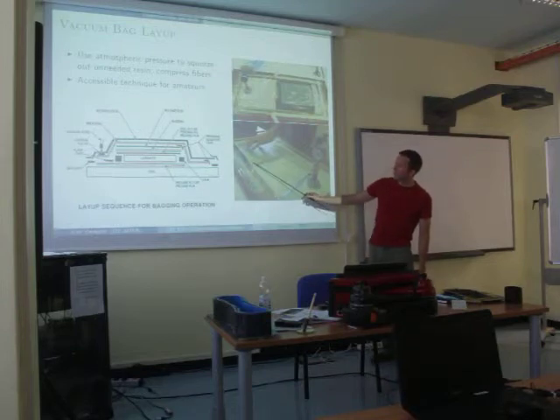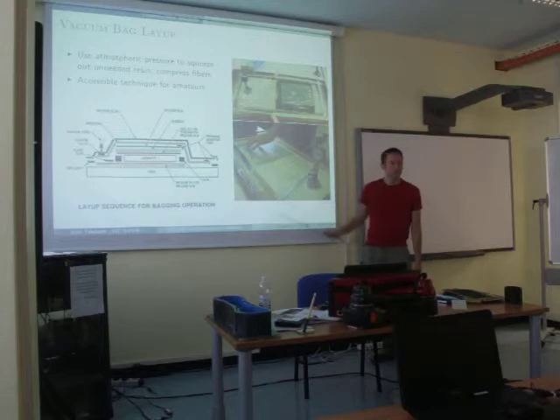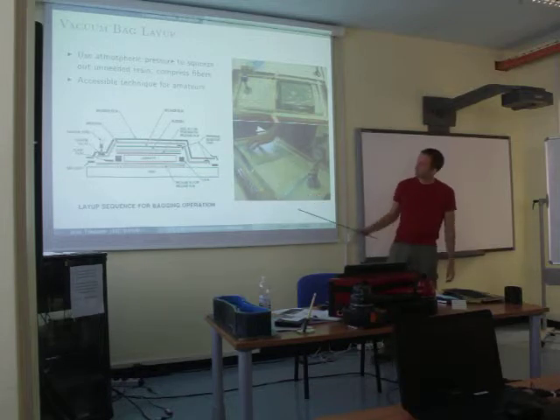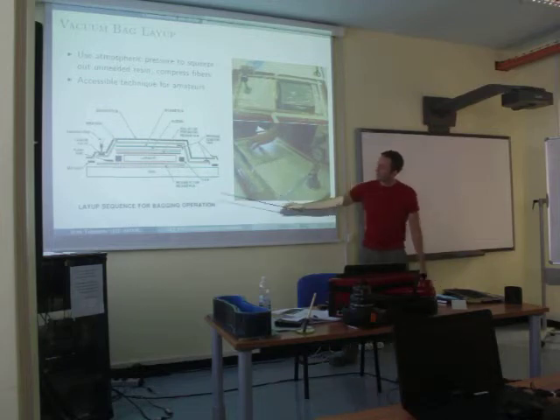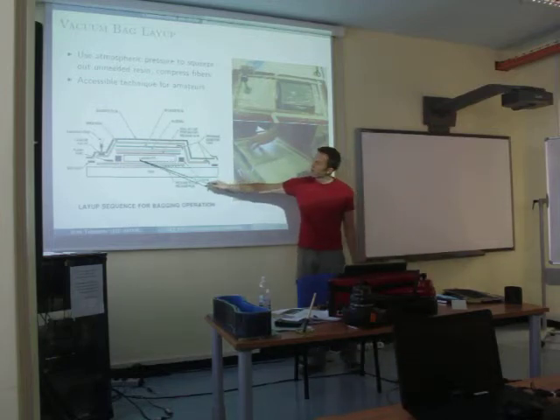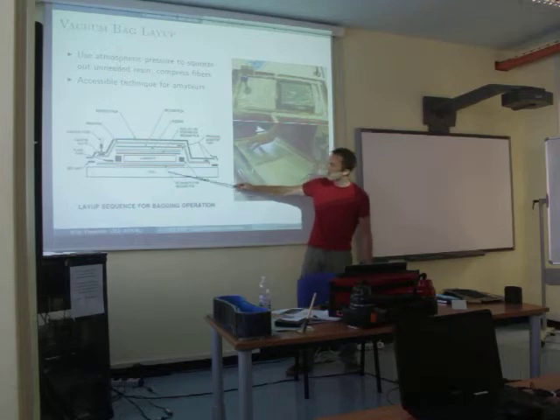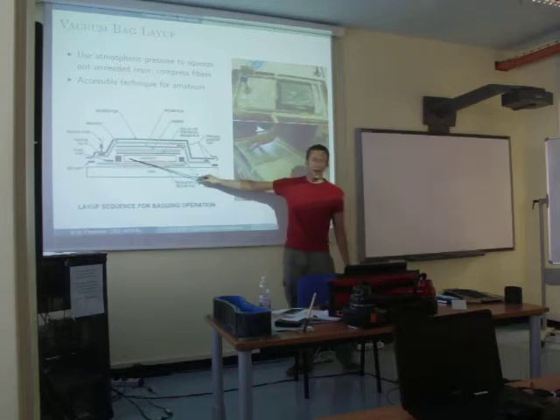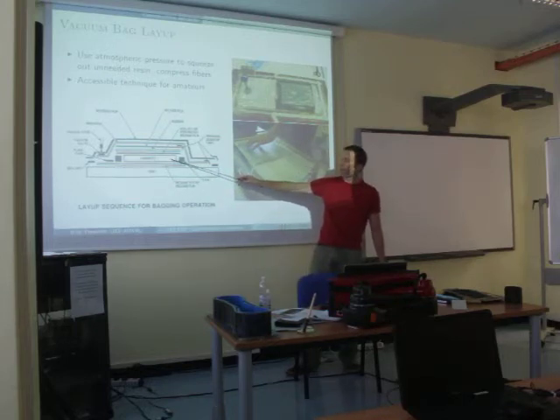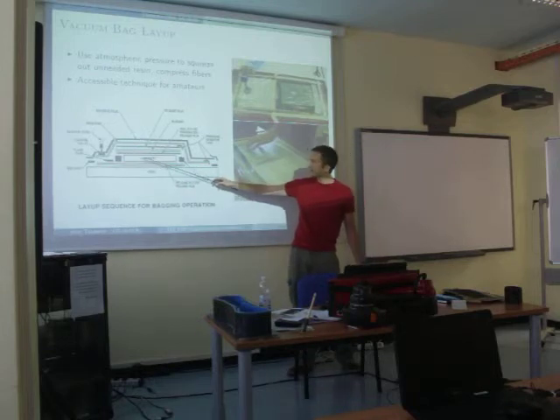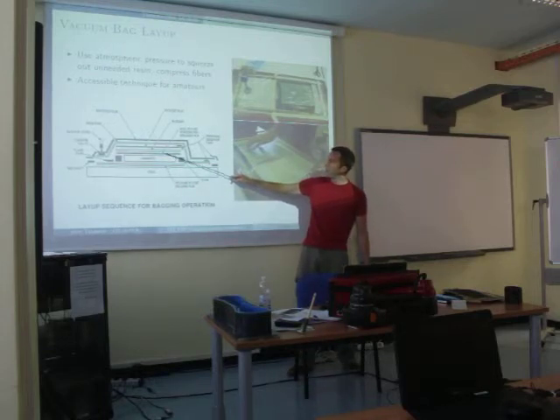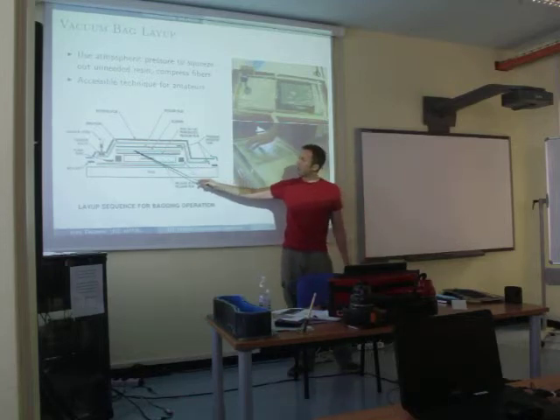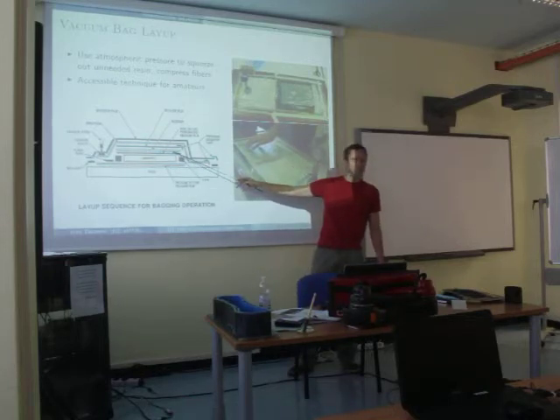Anyway, if you look carefully, you can see here that there are little dots as the resin has seeped through the perforated pink film. So for the part itself, there's the tool, the shape that you want to form. Then there's the stack of carbon fiber, which you wet out with the resin. Then there's a peel ply if you want, or a release film. Then there's the bleeder, that white stuff that absorbs extra resin.